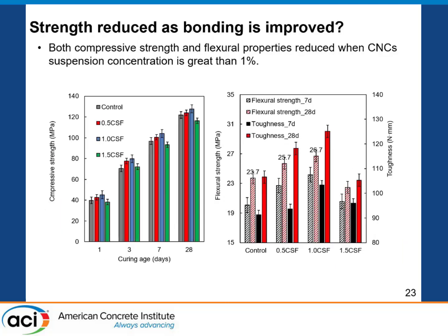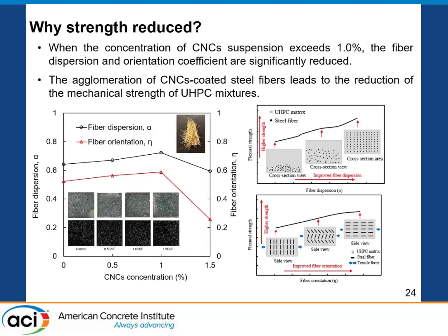However, we have the improvement, but we also have the reduction. As I mentioned, when the concentration is around 1.5%, we have the agglomeration, and we cannot really break the bond between the fibers. Maybe some of you have a better solution. Because of this, we could not have a good fiber dispersion in the system when the CNC concentration is greater than 1%. We always need a good dispersion and orientation to get better flexural properties. Anyway, this is why this reduction happened. I just want to emphasize that.